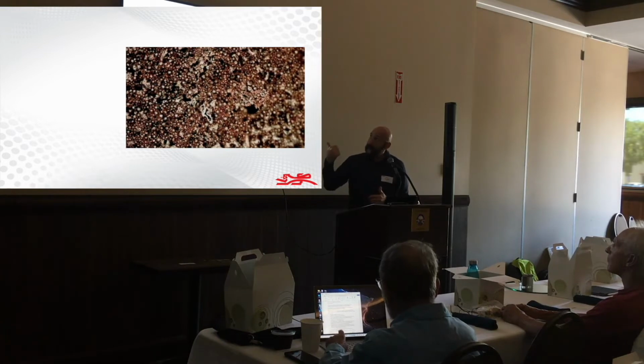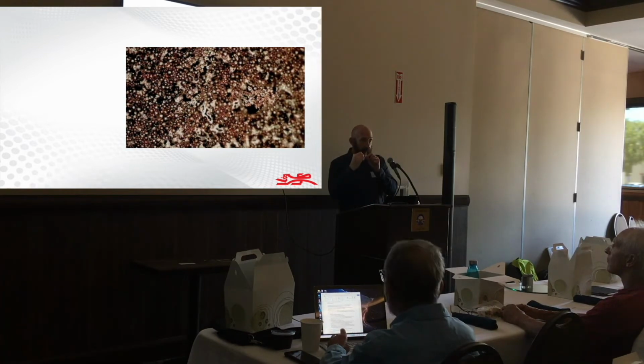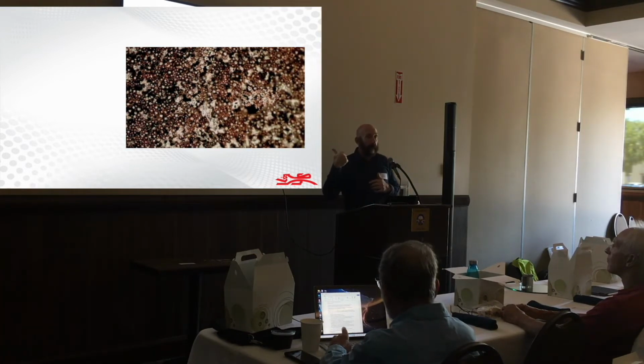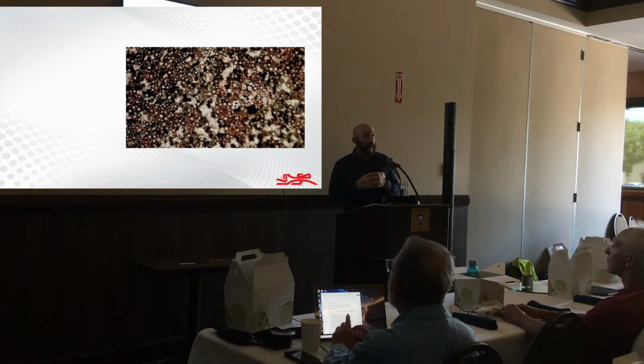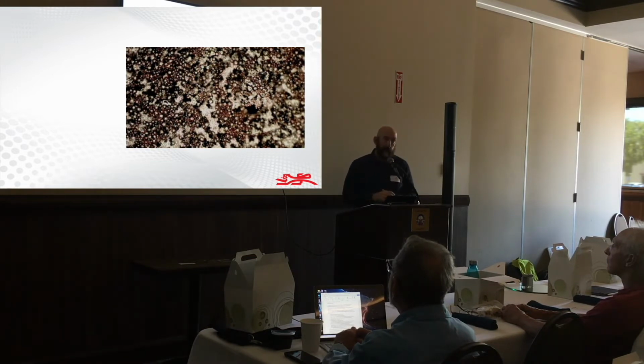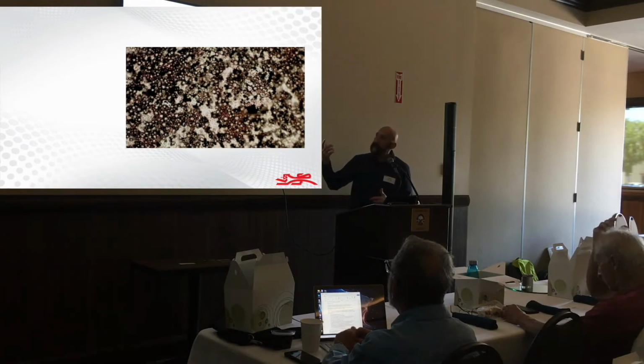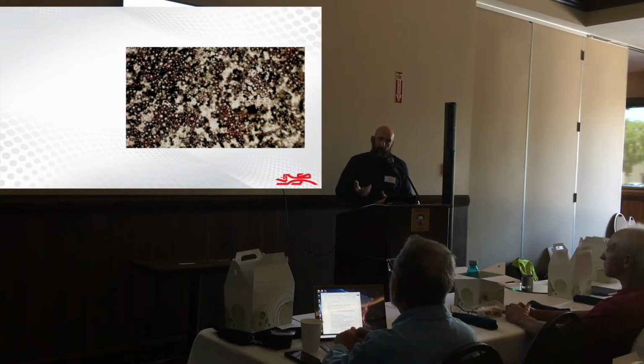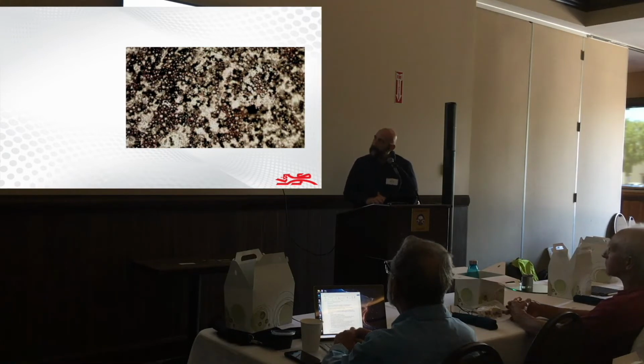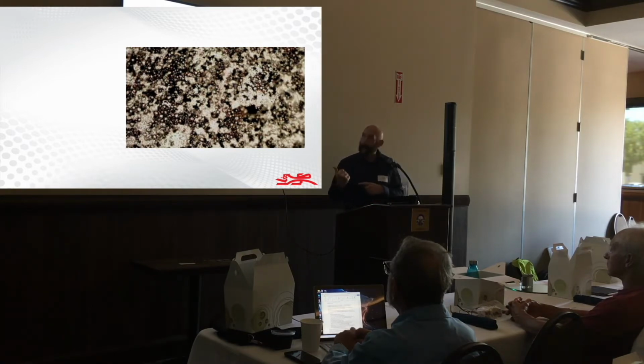One thing you'll notice is this is just between two glass slides. Notice how there's no bubbles, right? So imagine this happening inside the dielectric of an inner layer or multiple layers in the lamination process of the PCB fabricator. So it's very important that part of the paste technology is the system that removes the oxide shell from the copper and allows the tin to form that alloy without producing any bubbles or any other artifacts that might affect the PCB. Probably getting into more detail than you want.